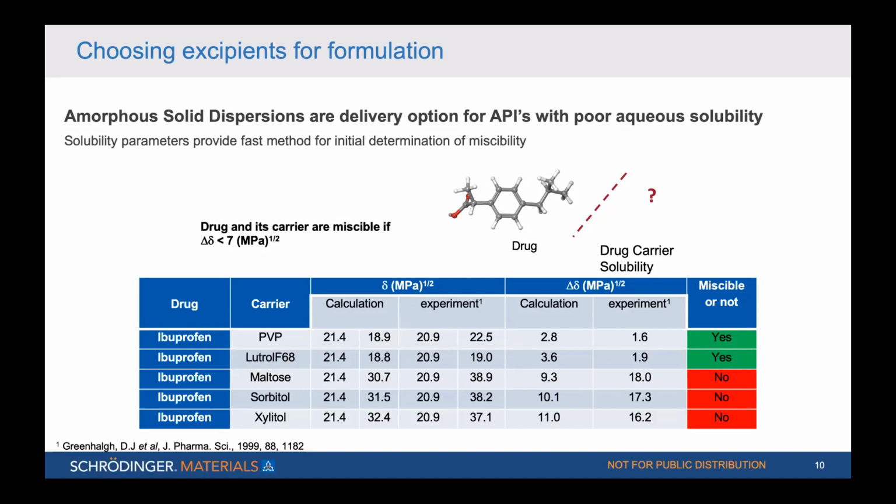So that cohesive energy can be used to calculate something called solubility parameter. Hildebrand solubility parameter, Hansen solubility parameter. There are two different types of solubility parameters that are there. We can calculate both of them. So once we calculate these Hildebrand and Hansen solubility parameters, they can tell us whether particular components are going to be miscible with each other or not. When you are putting them together, they are going to be happily interacting with one another, or they're going to phase separate from one another. When you are putting them inside a particular solvent, whether these two components are still going to be interacting inside the solvent, or they're going to completely go away from one another.